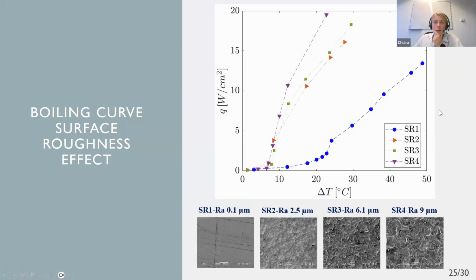For this kind of fluid, I don't have plots to show this now, but we observed some degradation of the surface using this fluid, meaning that the surface roughness with time was essentially decreasing, meaning that our boiling curves would tend to shift again towards the right, so towards larger excess temperatures. And this is something that needs to be further investigated.